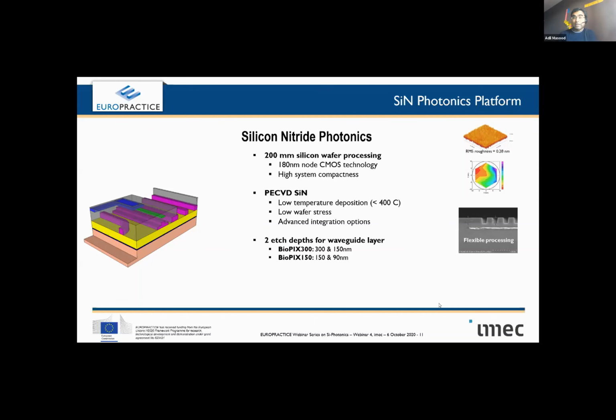Nevertheless, Imec offers two thicknesses, 150 nanometer and 300 nanometer, which can further be etched down to 150 and 90. These numbers largely came from a European Union project called PICs for Life, which was probably the first major initiative in Europe to kickstart MPW services for silicon nitride. That does not mean that silicon nitride MPW services did not exist before, but this particular project focused on life sciences. And that is why the wavelength range was selected as 400 nanometer to 1000 nanometer.